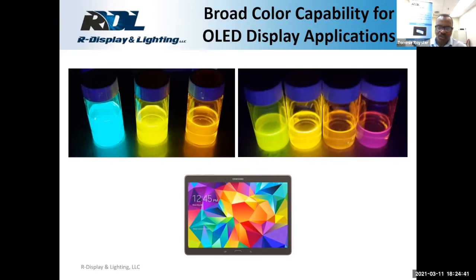One of the things that has been preventing the implementation of an efficient blue emitter is that the extended lifetimes of phosphorescent emitters end up resulting in degradation pathways that degrade the OLED device very rapidly because of the high energy of the blue light. So the objective is to establish materials with a short excited state lifetime on the tens of nanosecond scale, as opposed to the microsecond scale in which you find yourself with most phosphorescent emitter materials.